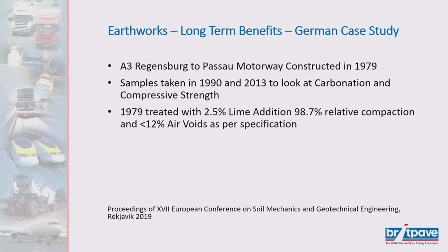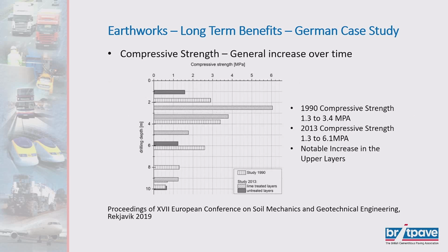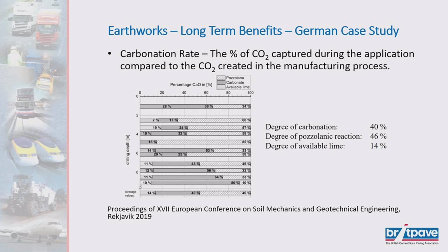A lot of more granular soils in Germany, so they tend to have a higher air voids allowance than we would normally allow within the UK. Very simply, it's treated with lime. In 1990, they were getting average compressive strengths of 1.3 to 3.4 MPa. That was going up to some places 6.1 by 2013. So it is still increasing in strength over time with the addition of binders, and with a notable increase in the upper layers.